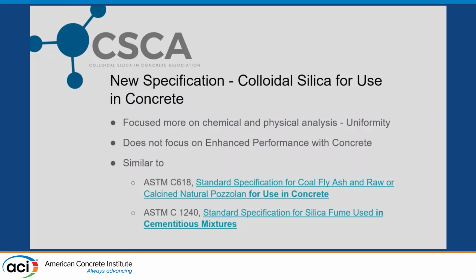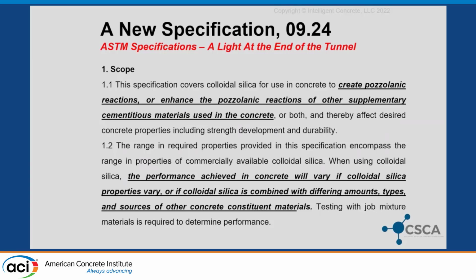And this approach that we took for the ASTM was focused more on a physical and chemical analysis for uniformity, not focusing on performance-based testing as you would in the 494. And we find that more practical for the manufacturers and distributors out there. And you'll see it in our scope of work, where we talk about what the colloidal silica is used for. The most important part to me is that the performance achieved in concrete will vary. So creating a strength activity index, where you have to get at least this or no more than that, is a very difficult thing to do, because not all colloidal silicas are created equal.